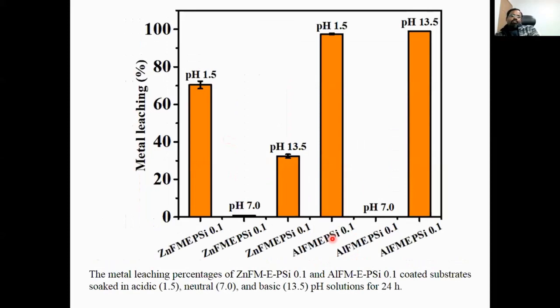We further checked the coated substrate stability against acidic, basic as well as neutral media by keeping the coated substrate in different pH solutions for 24 hours. Then we checked the metal ion leaching from the coated substrate. It shows that because of the dissolution behavior of aluminum in basic medium, as well as zinc in acidic medium, some of the metal source can leach out. The aluminum in basic medium almost comes out completely. So it is not so good at strongly acidic or strongly basic media, whereas at neutral pH our coated materials are very stable.